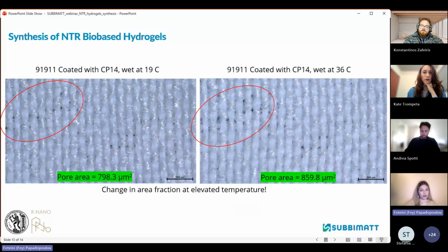And since we are trying to work with a hydrogel that does change with temperature, does the temperature indeed change it on the fabric? So we tried and tested that. These pictures are from a stereoscope, again, using a hot plate underneath. And here especially, we took a picture on the wet fabric, coated with a cross-linked hydrogel on top of it. And we actually observed that changing the temperature from 19 degrees to 36 degrees does change the pore area that can be observed.